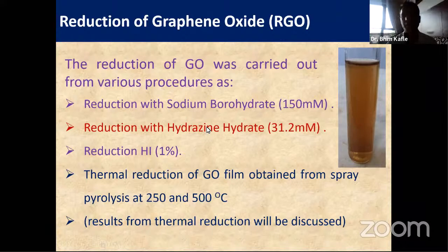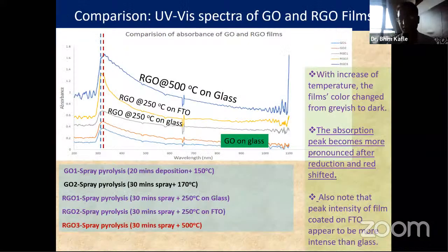We found that reduction by hydrazine hydrate was the best one, and then we tested an alternative method. First we prepared a film of the GO by putting this solution on glass, and then heated our sample up to, let's say, 500 degrees centigrade. You can see that with increasing the temperature of the substrate, the peak of this GO sample slightly red shifted. It means that it is not completely reduced, but partially reduced. So our sample is a semi-reduced sample.